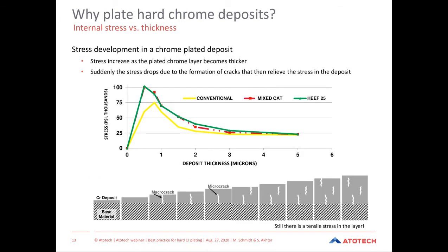So if we go and look at the next slide, which shows us what is happening in terms of the internal stress as the thickness is building up. So as the cracks form, we create a pattern of cracks which are staggered, because what tends to happen is within the first cracks forming, we get more deposition, those cracks are covered, and then the stress builds up again and the deposit cracks again. And this process is repeated as the plating progresses.